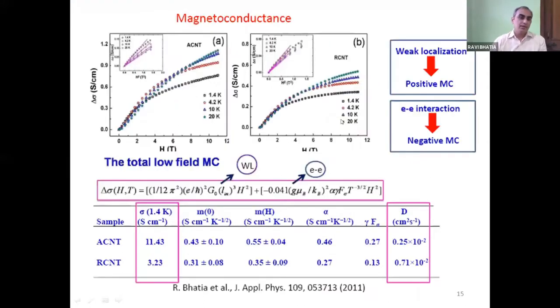It is very, very important in low temperature charge transport that one should corroborate the results from conductivity versus temperature with the magnetoconductance or magnetoresistance. Here one can see the two samples represent almost a similar behavior with the magnetic field at various temperatures below 20 Kelvin. But here you see there is a clear indication that there are two competing effects. Weak localization causes the positive magnetoconductance, and electron-electron interaction contributes to the negative magnetoconductance, but more or less still the same result.